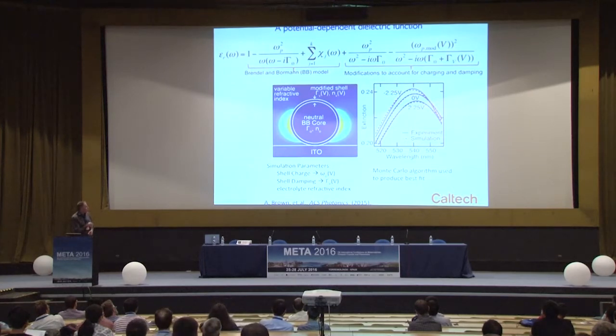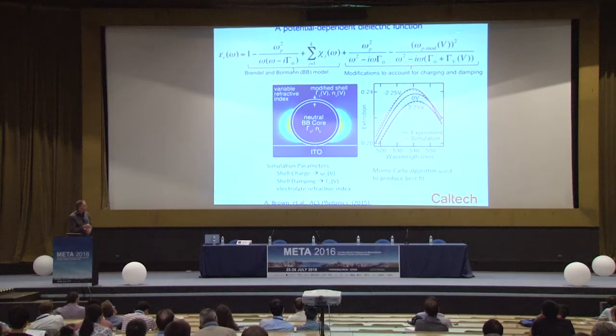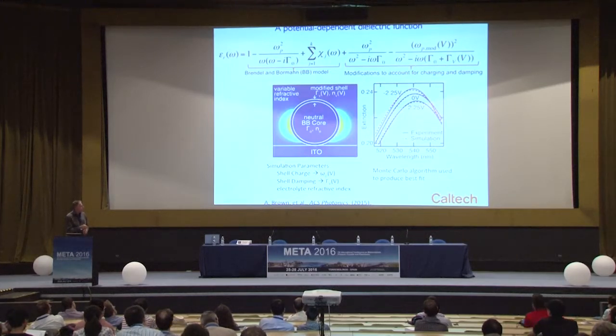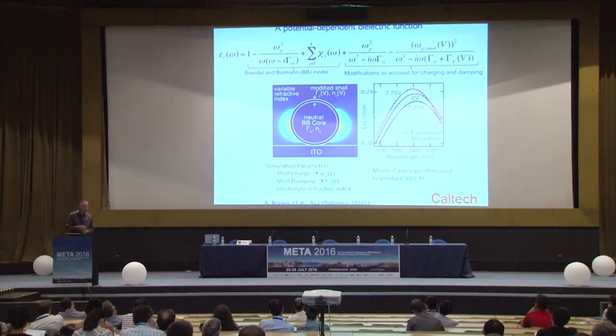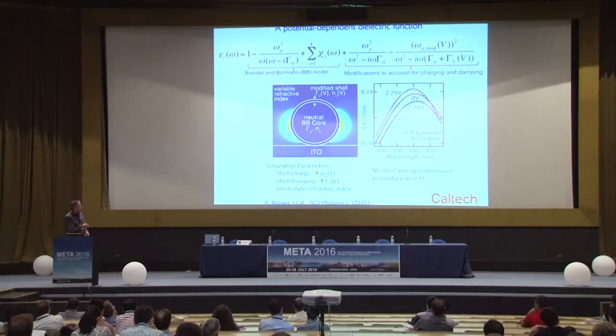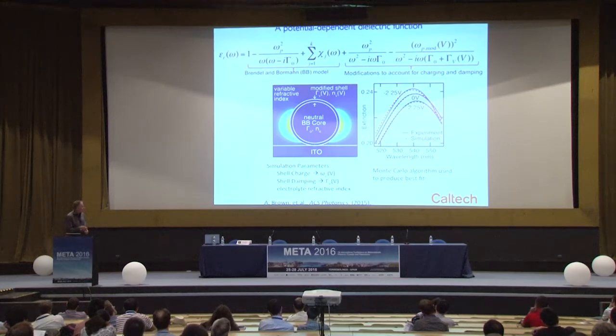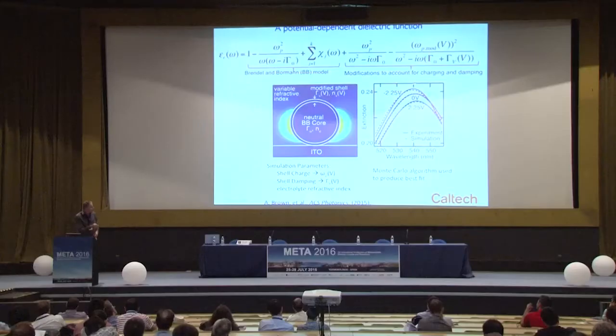But to really understand this, we have to now modify the complex dielectric function of a metal, incorporating potential dependent terms that account for the resonant frequency as we change the charge density and polarizability. But also, we find that this changes not only the resonant frequency, but also the resonant line width. And this is easy to understand because in a metallic particle, as we add and subtract charge, that charge, from simple electrostatic energy minimization considerations, is distributed in a thin shell interacting with the interface of the material. And as we polarize that charge, then of course that excess charge disproportionately engages in scattering with the surfaces and interfaces of the particle, and we see then that that produces changes in the line width. So indeed we can see that metals are tunable, and so by applying electrostatic potential we can tune the properties of metals.